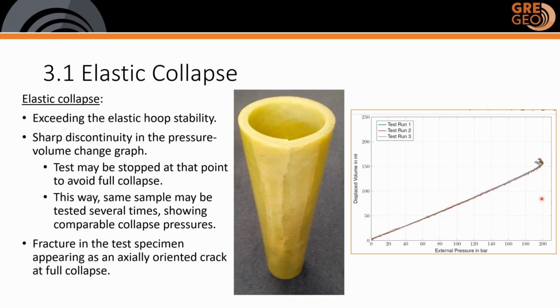We further observed that if the tests are stopped just above the instability point, unloaded the sample and reloaded again, the measured collapse pressure is comparable. So you see 3 test runs over here with almost the same level of elastic collapse pressure. And that's also an indication that to a certain extent, this mode of failure is also reversible. The characteristic of this pipe failure is a long longitudinal crack, as you see over here. And again, this is typical for an elastic collapse type of failure.